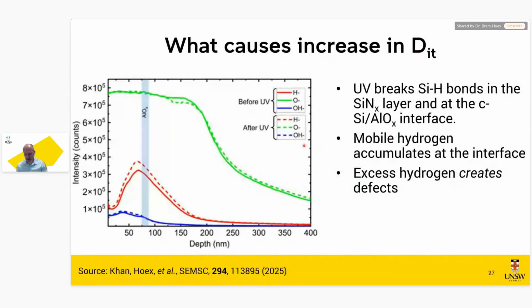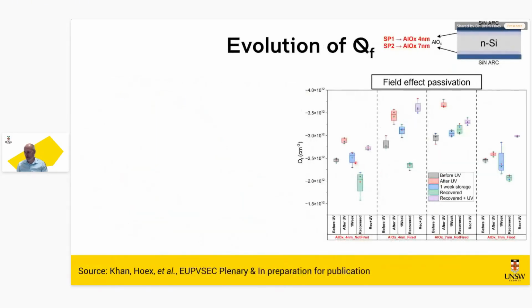And this is the evidence we have for this hydrogen piling up at the interface. So these are time of flight SIMS measurements. So we're counting fragments. We remove a layer and we count what is removed from the layer. And then we count the mass, and then we can assign certain fractions we measure to hydrogen. And we see that in this case, we see a significant increase after UV at the interface. So we see hydrogen piling up at the interface, and it's not very well known, but experts in the field know that too much hydrogen is not good. Too much hydrogen actually creates defects. A low amount of hydrogen is good. It's good for passivation. You can have too much, and that's what we believe is happening here. But we don't have the full solution. So we also have to look at the fixed charge density. So under UV, QF increases.